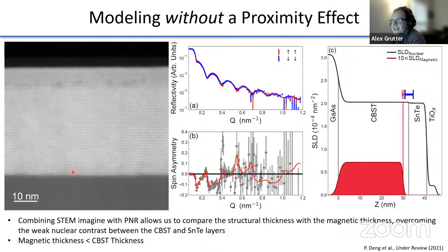And this turns out to be a ridiculously difficult neutron reflectivity problem. The reason is obvious if you look at the nuclear scattering length density profile here, where chromium doped bismuth antimony telluride and tin telluride look exactly the same to the neutron. Even though we grew a very special sample for neutrons, with really thick chromium doped bismuth antimony telluride on the bottom and a nice tin telluride layer on top, you just can't tell where one layer stops and the other starts from the neutron reflectometry.